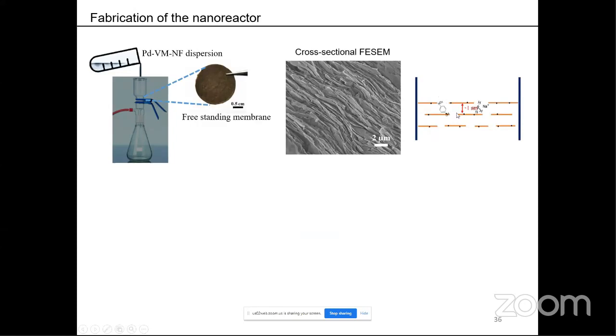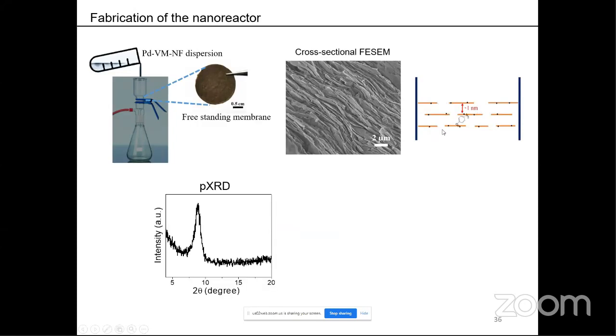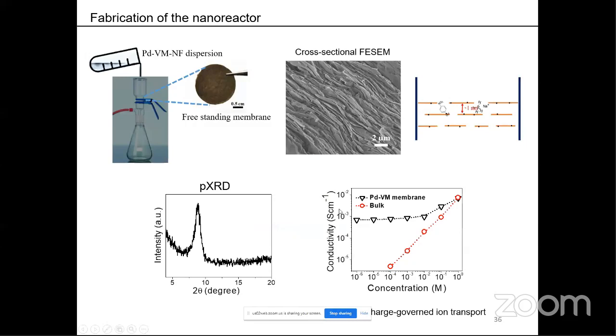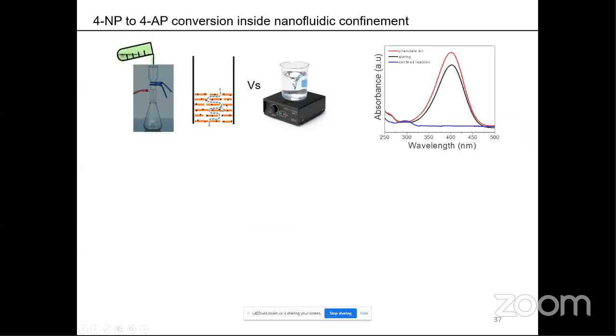You can see, and through this confinement, we want to carry out the reaction. We have characterized through confinement analysis as well as XRD patterns. Now, when we put our reaction mixture, sodium borohydride and nitrophenol, through this membrane and compare the result with the stirring condition, we have two reactions, one inside the confinement, one inside the stirring condition.